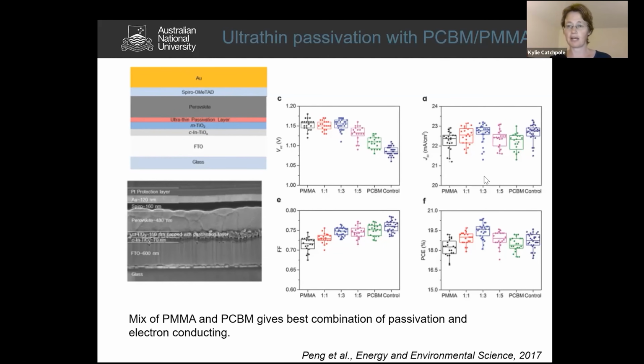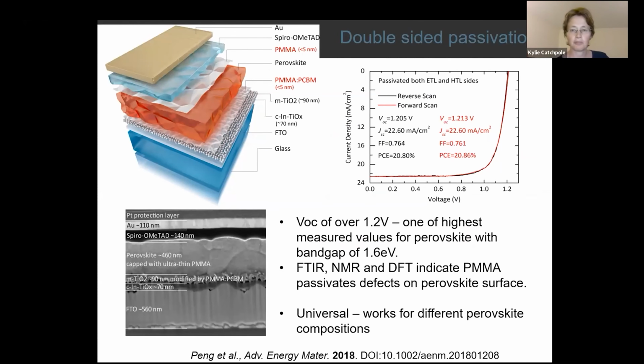increase the voltage, but also have an increased fill factor and overall higher efficiency by having that combination of PMMA and PCBM. And the reason is that the PMMA is insulating and the PCBM is conducting, and so that allows some balance of passivation and conduction by using that mixture. So we moved on from there to a double-side passivation approach, and this was applying a PMMA layer to the other interface in this case.